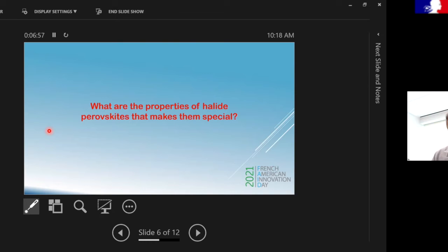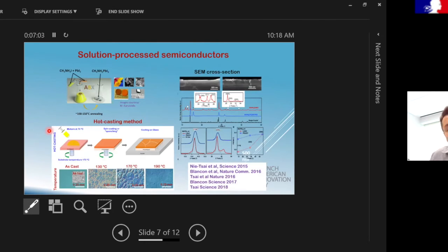We saw this rise in efficiencies. And so what's so special about them? And so it turns out the first thing is that these are solution process materials. So you can use dirty chemistry, put them in solvents and create very large crystals of this, or make thin films like we did here in this case. And these are some publications, which over the years that have come out on our work.